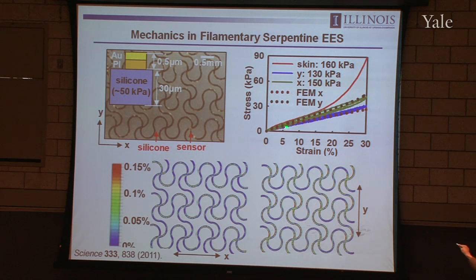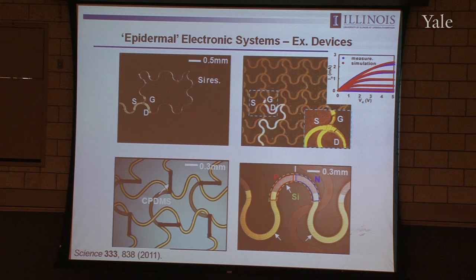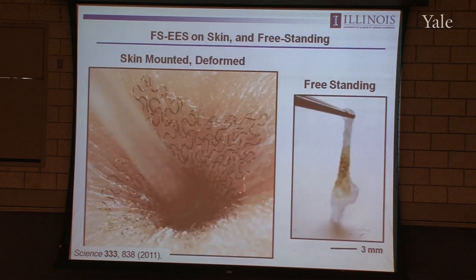This is pig skin, actually, here. So about 160 kilopascal. And for this circuit, stretched along that direction or along that direction, the modulus is almost identical. Up to strains of about 20%, and then actually the modulus of the circuit is lower than that of the skin, but skin starts to tear above 20% strain. And you do all the FEM modeling, so you know exactly what the peak material strains are in that kind of design, and you can manage that in an effective way. Now the key thing is you can build all of your devices in that wavy snake-like geometry. So you can cut your silicon like that, you can make a transistor that's in this funny geometry, it still works fine. You can create strain gauges, even solar cells, photodetectors, temperature sensors, capacitors, inductors, LC oscillators, all kinds of components can be configured into that type of platform.